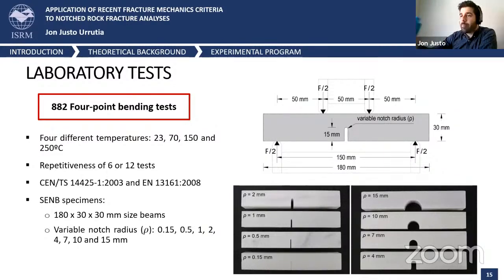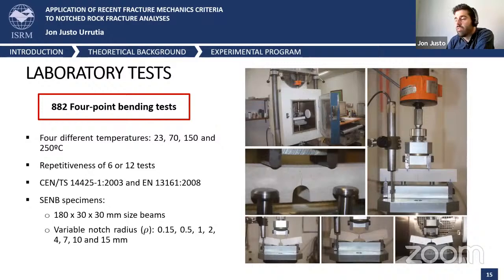So first, the 4-point bending tests have been performed at different temperatures from 23 to 250 Celsius degrees, with a repetitiveness of 6 to 12 tests in some cases for verification purposes. There you have some pictures of the used samples, which consist of 180 times 30 times 30 millimeter size single edge notch beam specimens with variable notch radius from 0.15 up to 15 millimeters. Those samples with the smallest notch radius, those with 0.15 millimeters, were used to calculate the value of the fracture toughness, and the rest of samples were only used for the interpretation according to the theory of critical distances and the strain energy density criterion, to compare the experimentally obtained failure loads with those of the fracture predictions. Here you have some pictures of the performed test.